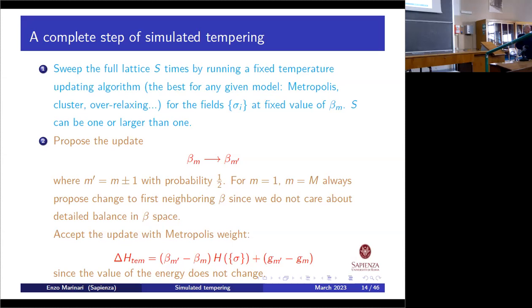So you say beta goes to a nearby value of beta, or the probability of accepting it would be 0, right? So m prime equals m plus or minus 1 with probability 1/2. On the boundary of the allowed beta values, you don't care, because indeed you don't care about Boltzmann equilibrium in the beta space. So it's okay, you can go with probability 1/2. In this case, you compute the variation of the tempering Hamiltonian. You see, the macroscopic energy of the system doesn't change, but beta changes. So you would have that this factor changes, and then G would change. Okay. So delta H is done like that.